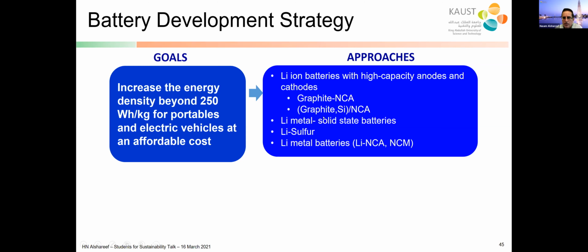For example, using different cathodes, I will describe in a second, or doping the graphite with a little bit of silicon, not a lot, just a few atomic percent of silicon, using solid-state batteries, and using lithium sulfur or lithium metal. This is basically lithium-based technologies that can take us beyond 250, possibly up to 400, 450.